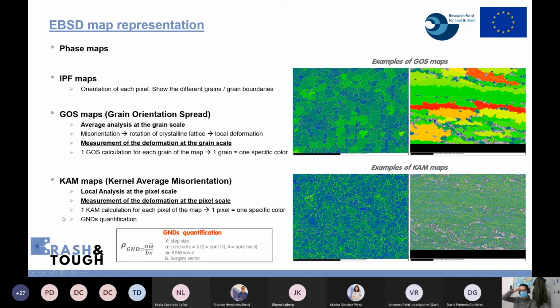And finally, the KAM maps, which means kernel average misorientation. Here we look at the local misorientation at the pixel size, and the same hypothesis: locally, if we have some misorientation, we can say that we have some local deformation. So here one color equals one pixel. And through the KAM maps, we are also able to quantify the GND, the geometrically necessary dislocations, through this formula, which consists of the step size, a constant, the KAM value, and the Burgers vector.